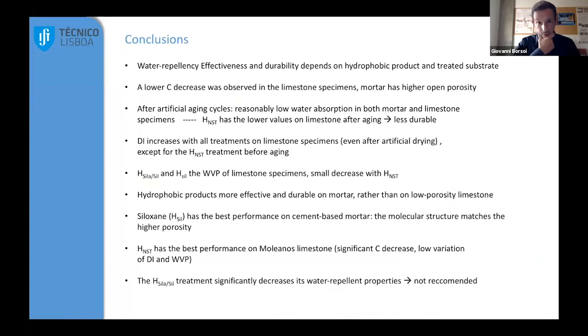So to conclude, since I'm already almost out of time, the main lesson I would say is that you need to fine-tune the effectiveness of the water repellent based on the properties of the treated materials, and of course based on the typology of hydrophobic product that is applied on those materials. For example, the limestone has a much lower absorption compared to the mortar, so you need to consider this. You need to look for something that is somehow respecting those physical properties.